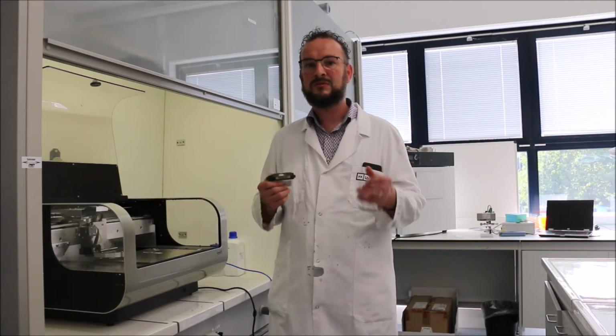The first system I would like to show you is this inkjet printing system. It's a drop-on-demand inkjet printing system that generates droplets of around 20 to 30 micrometer. These droplets then are guided towards the substrate where we can make nice structures having a line width of around 50 micrometers and a thickness of around 200 nanometers. The materials we focus on are, for example, silver nanoparticle inks, graphene-based inks, PEDOT:PSS, but also diamond nanoparticles that we, for example, use for heater applications.